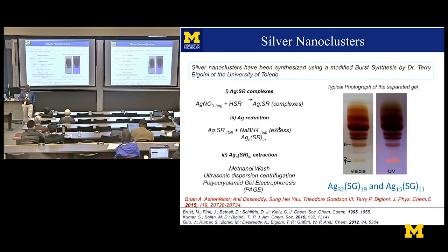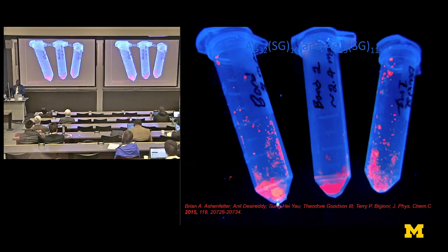So you need another method to make these. Terry at University of Toledo was the first to make very large quantities of this silver cluster. You can see this is with silver nitrate. You can do the complexation, and then you reduce that with the borohydride, and you make the extraction, and you do this wash. And then an interesting thing is using these kinds of PAGE gels, in which the thing that you want gets stuck in the gel, and you cut the gel and then dissolve the gel, right? So you isolate it and capture it, and then instead of going back to the original flask, you just cut the gel and take it out of the gel, right? Interesting, okay? And he was able to make the two known silver magic number clusters at that time, 15 and 32. And what's so interesting about these is that these silver clusters had enormous fluorescence.